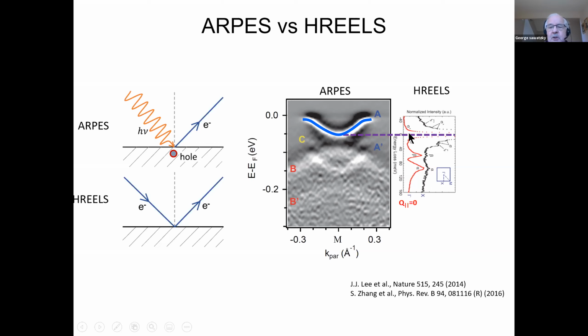And you see that those peaks, so this is the zero loss line here, and the peaks that you have, there are low energy phonons, of course, but then you have a peak here at about 60 milli-electron volts, and actually you can see this replica band here also. Okay, and it lines up with this peak here.